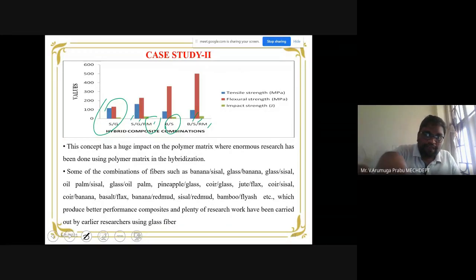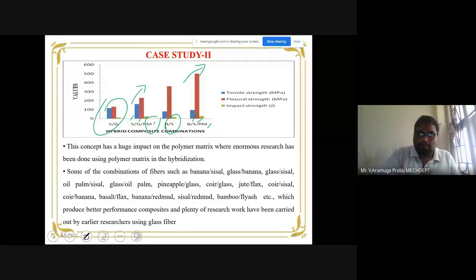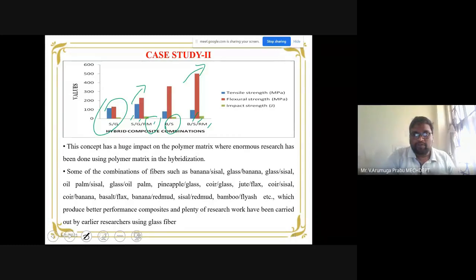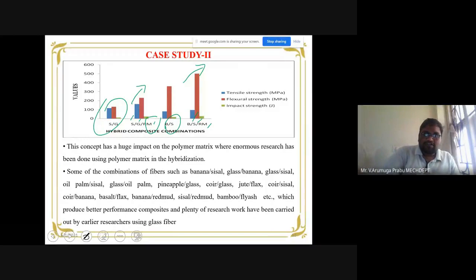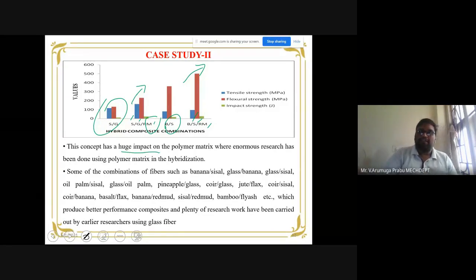Now you notice the peak. Please notice this color. These three colors go in an increasing trend with the addition of filler. So in all the cases, interestingly, the increase in the mechanical property values is clearly identified. Okay. So this concept is going to produce a huge impact in the case of polymer matrix, where enormous, exhaustive research has been done using polymer matrix in hybridizations.